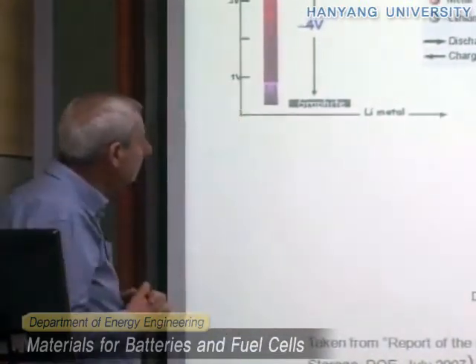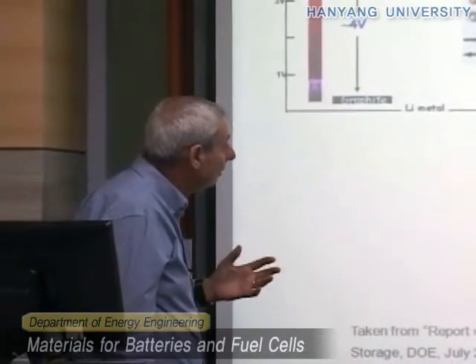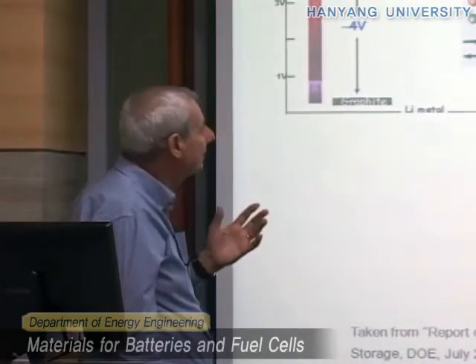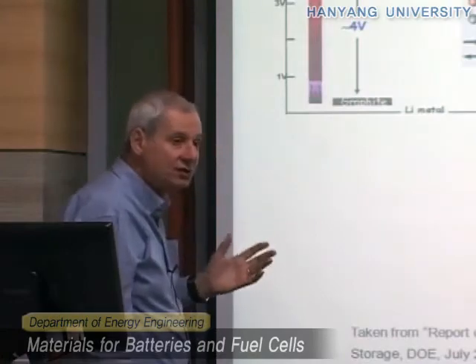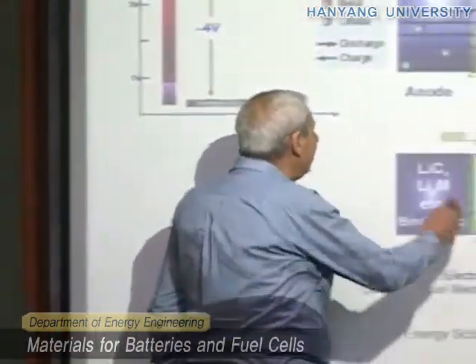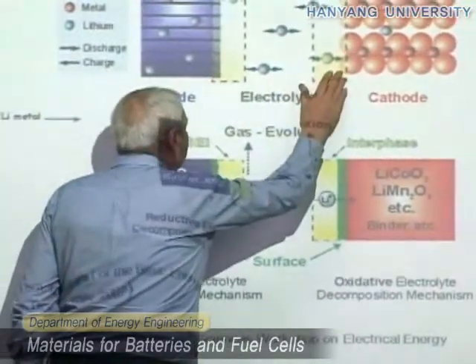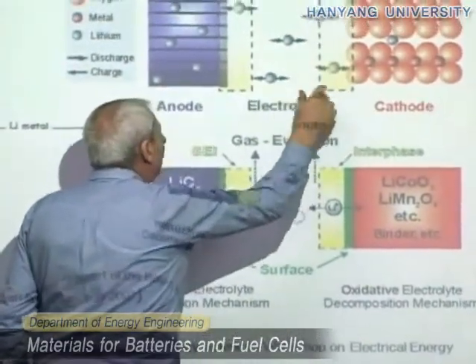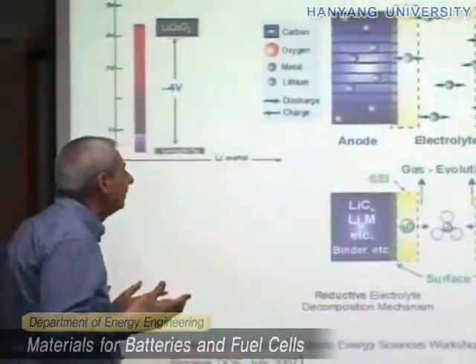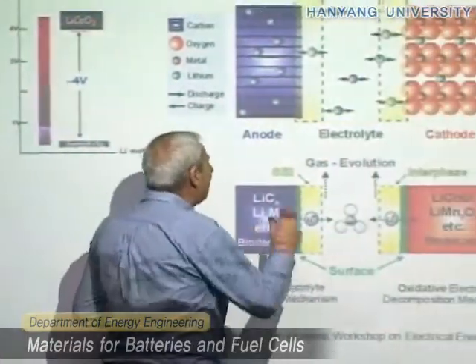When this happens, you have a reaction of the electrode material with the electrolyte, with decomposition of the electrolyte and formation of this film. The decomposition of electrolyte is also associated with the formation of some gas and other byproducts. This film does not allow transfer of electrons so that the decomposition of the electrolyte is stopped, but it does allow lithium transfer.